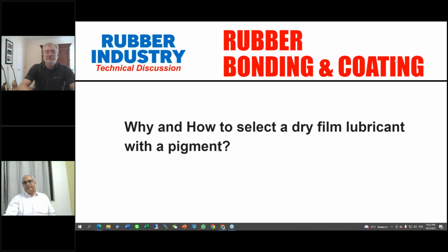So this selection of the film lubrication with the pigment is a very important aspect as compared to only the black color, that is the graphite or the molybdenum disulfide. Because especially with the black color, you cannot add any additional color over there, and that is one of the limitations of that particular dry film lubrication application. And with the PTFE, you are able to achieve these features, and you can achieve the corrosion resistance part of it with the pigment addition actually.